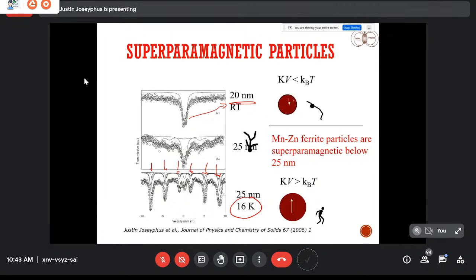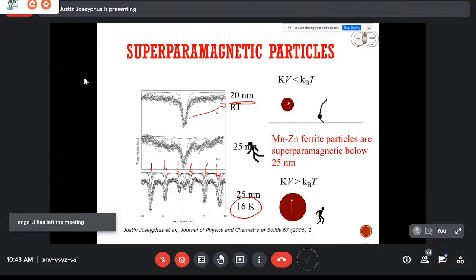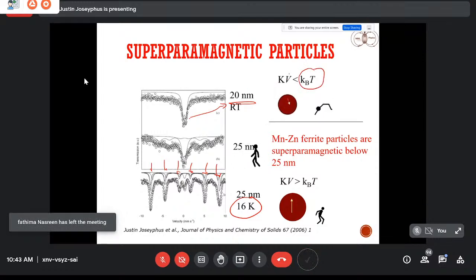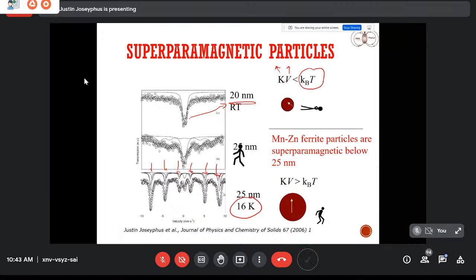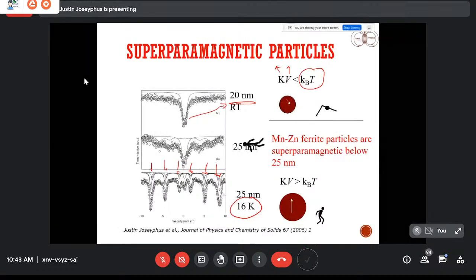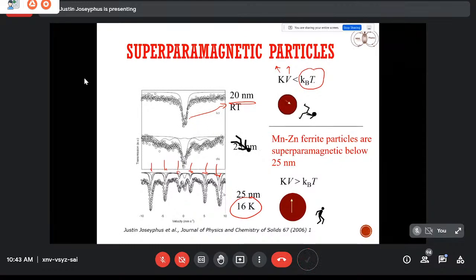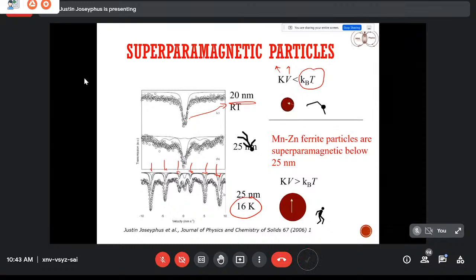Relaxation means your magnetic spins are rotating very fast when your size is small. Why? Because the thermal energy becomes dominant. V is the volume, K is the anisotropy. When your volume reduces, the thermal energy dominates, and your magnetic moments fluctuate. So the effect of thermal energy is to fluctuate the magnetic spins, and as a result you have a double line pattern. But when your spins are stable, you have a 6-line pattern. So in the case of Mn-Zn ferrite, we have established the critical superparamagnetic size from Mossbauer spectrometry.